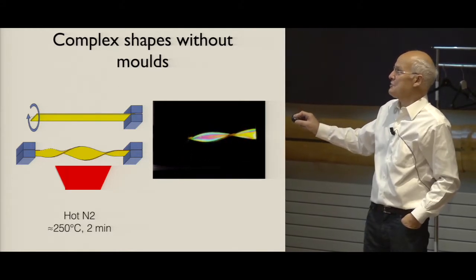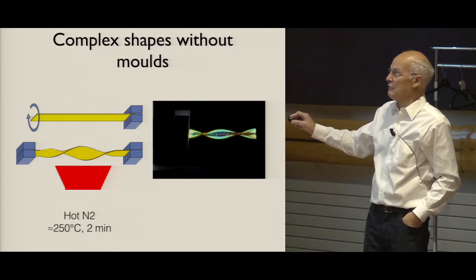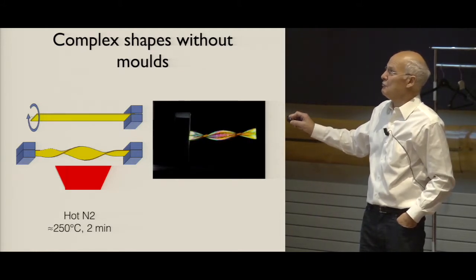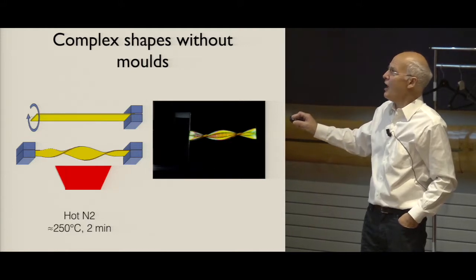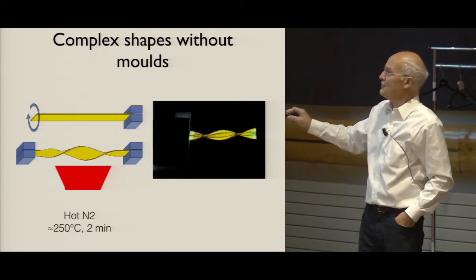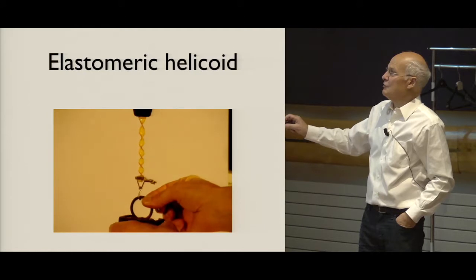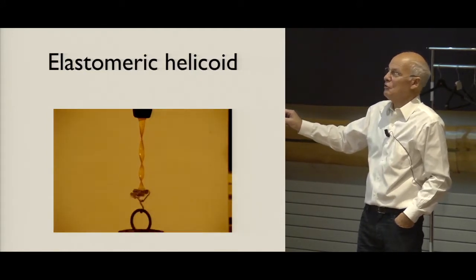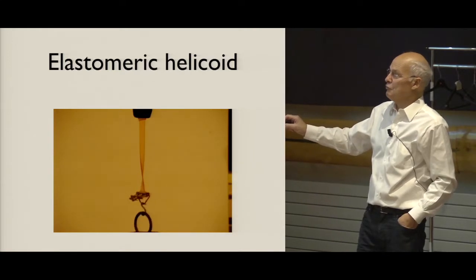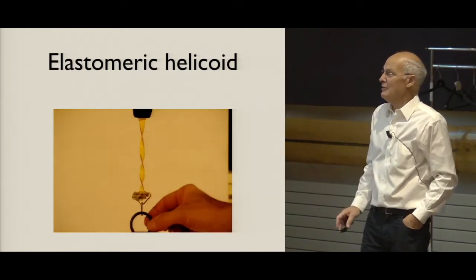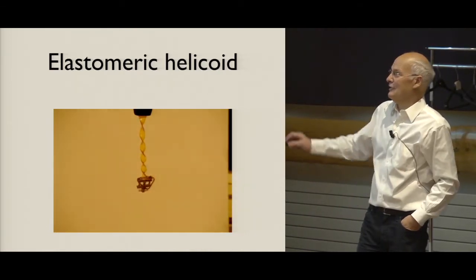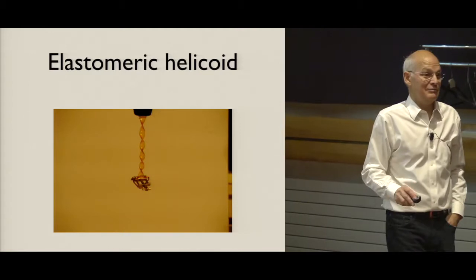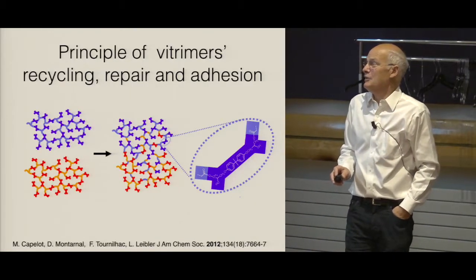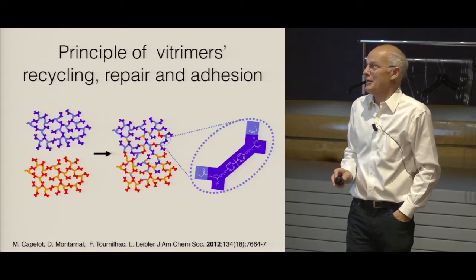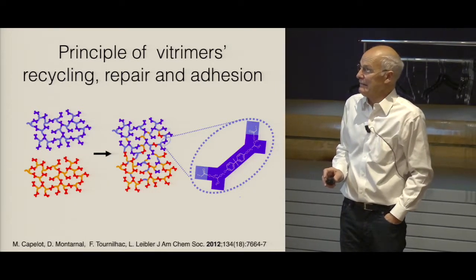Here we deform it. The stress is built up, so you see it becomes birefringent, and then, you cannot hear it, but we put this hot nitrogen blower, and the stresses relax, so the birefringence disappears. And then at the end, what we get is a new shape, which we obtained without mold, without anything. And if we put a weight on it, it deforms like an elastomer, and then we relax it. So we can reshape it without a mold, like a glass blower reshapes a glass.